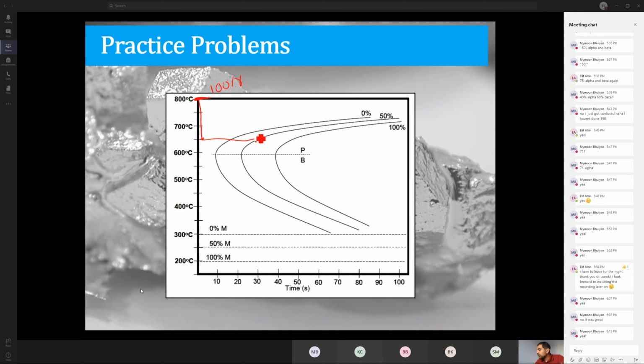Well, let's look at the diagram. It says above this line here, we have pearlite, or we make pearlite. And these lines here tell me how much pearlite I've made. So starting here, I begin to make the pearlite. By the time I get to this line, I made 50% pearlite. So after 30 seconds, I have 50% pearlite. And what's the rest of my material? The rest of my material, the other 50%, is gamma or austenite.